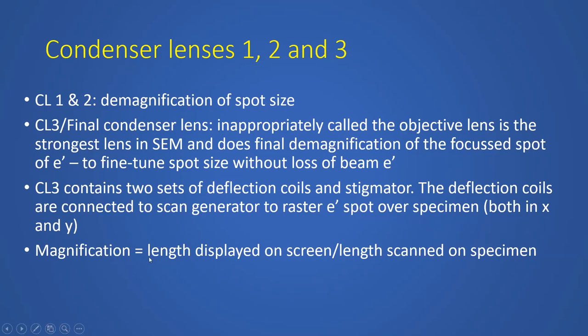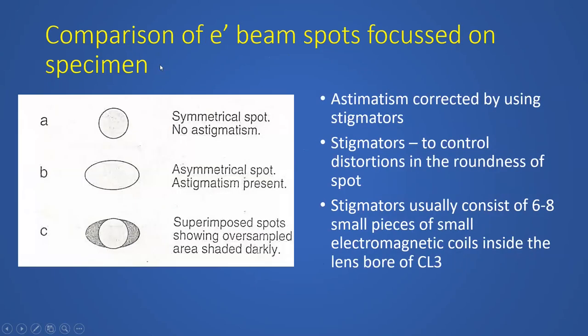And in SEM, the magnification is basically the length displayed on the screen divided by the length scanned on the specimen. So if the length of the object you're looking at on the screen, if you use a ruler, is 10 centimeters, and the length that is scanned on the specimen inside your chamber is 10 millimeters, the magnification will be 10 times. It's as simple as that. The length scanned on the specimen is on a much smaller scale, like 10 millimeters, and if the length on the screen is 10 centimeters, magnification will be 10 times.